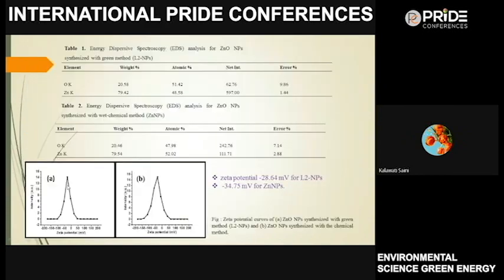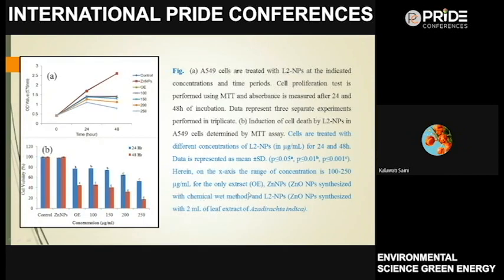0.98%. These are the zeta potential study. Zeta potential regarding green is minus 28.64 millivolt, and for chemical method 34.75 millivolt. It means both are stable particles. These are the results regarding L2 nanoparticles.